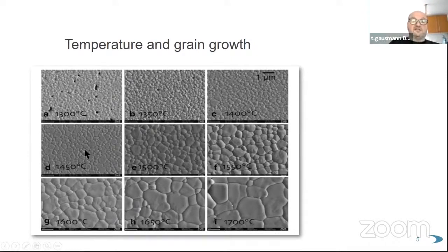1450 degrees Celsius is the temperature to start. There you can start proper sintering. So our cubic material, for example, has 1450 degrees Celsius. 1500 degrees Celsius here in the middle is the optimum between strength and translucency. You have wider, larger grain borders, less grain border in the same space, meaning less scattering of light, more traveling of light. At the same time, you have a good connection between the grains. You get an atomic connection between the different grains, and this is still very strong, giving you a very, very strong material.